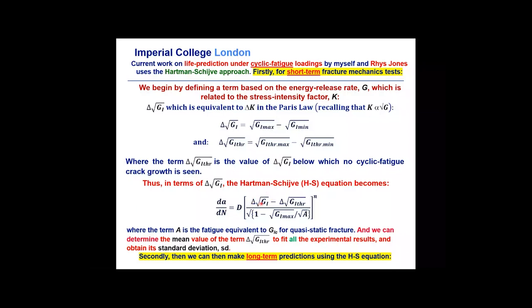Now we can do that by getting all the experimental data from short-term fracture mechanics tests, and we get one master curve, and we get that by varying somewhat the value of delta root G threshold. So by relatively small variations in this term, we can fit all our short-term data onto one master Hartman-Schijve plot. And that therefore gives us a mean value of this term. And we also get the standard deviation. So now we can use this term coupled with its standard deviation to make long-term predictions using this Hartman-Schijve equation. And the Hartman-Schijve equation is actually widely used in terms of stress intensity factors by metal engineers, metal aerospace engineers.